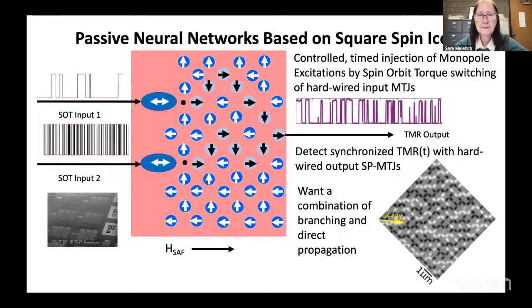There was a company, 15 years ago, that came up with a device that had 4 scanning probes on it. But the idea was you'd be able to do 4-point probe measurements on nanostructures, but it was extremely difficult to operate the tips independently. And so you would really have to hardwire one. You could have one scanning probe and one fixed probe. And with our experiments with the neural network, we're going to hardwire the inputs and then use the single scanning probe to go through the lattice.